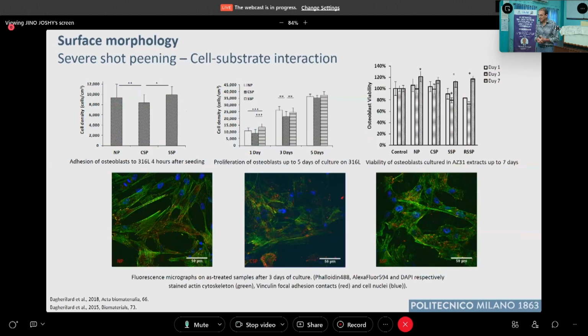Here are some graphs that refer to the biological tests that were done. Indeed, cell density. What is the cell density? The amount of cells that attach and remain attached to the surface of the 316L material after 4 hours after seeding, and then after 1 day, 3 days, and so on. And what can we see? That the effect of severe shot peening is more remarkable in the initial phase of the test, so after 1 day, and then at the end, after 5 days, everything is aligned. But this is also not negligible.